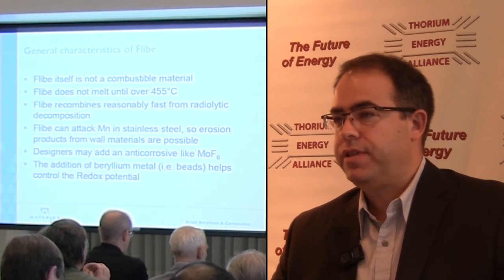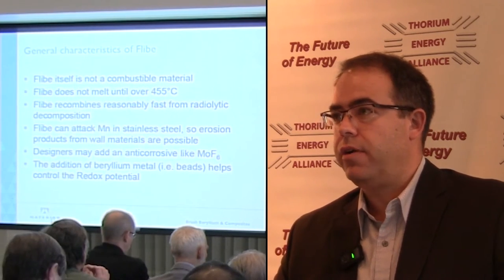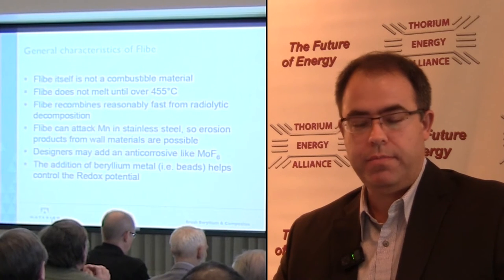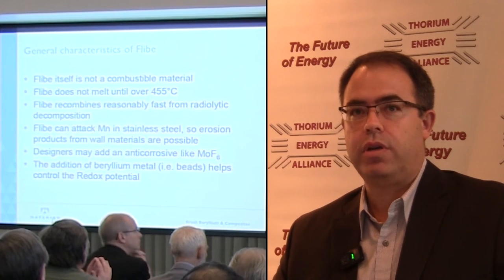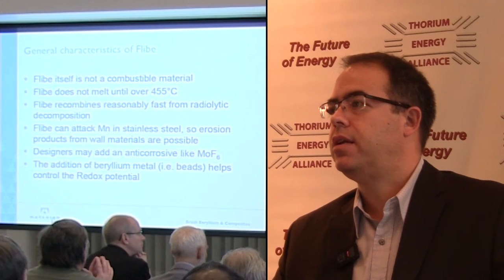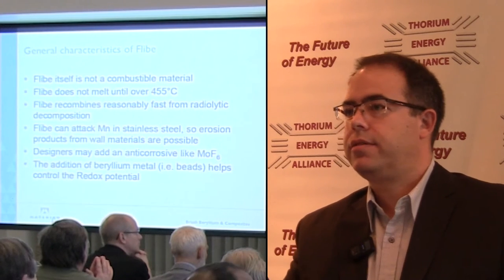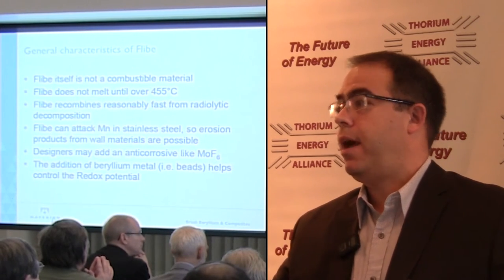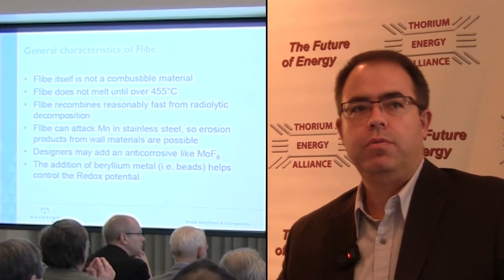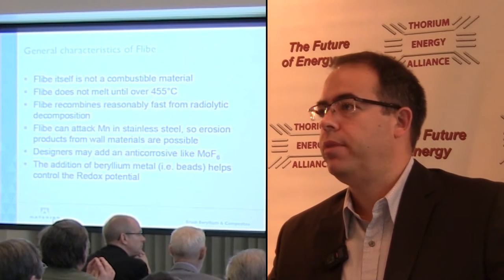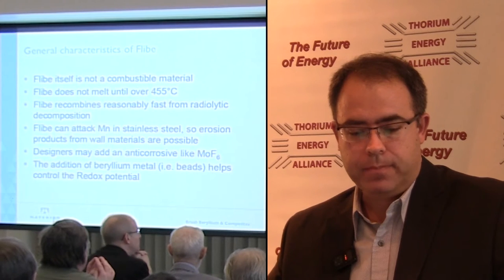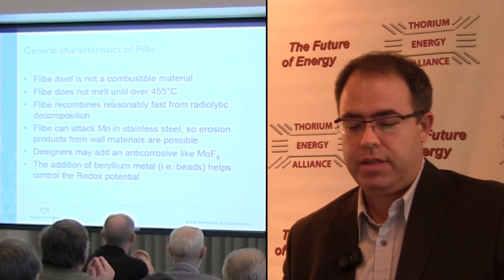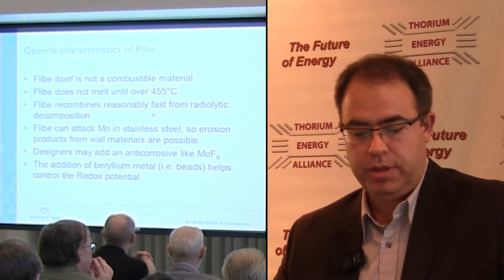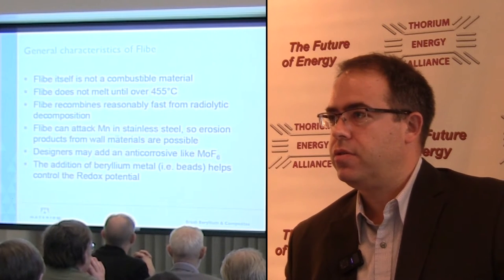Flibe itself is not combustible. It's a very stable material. It melts at slightly over 455°C, which makes it ideal. You form eutectics, for those that love thermodynamics, I love thermo. So you make low melting point materials. It recombines reasonably fast if it decomposes. Of course it has issues, it can attack.